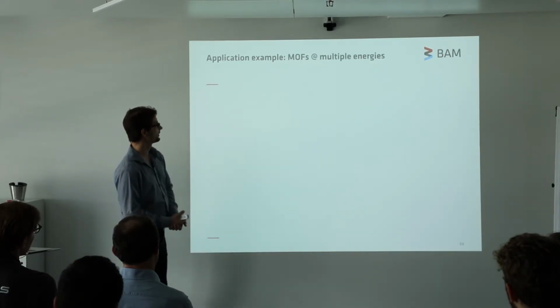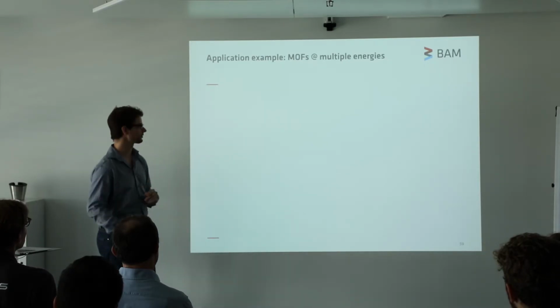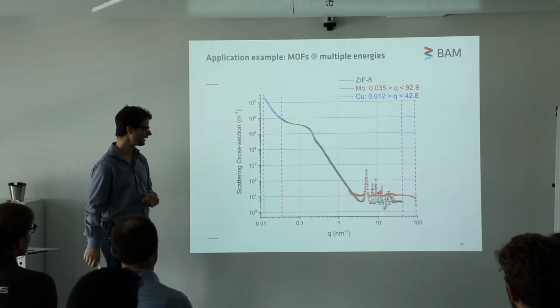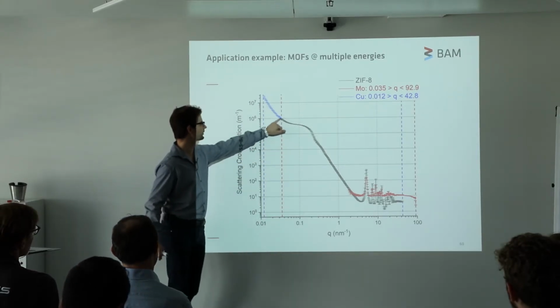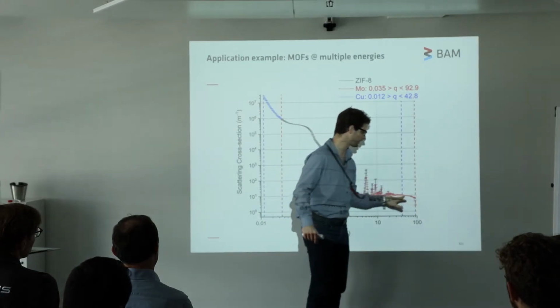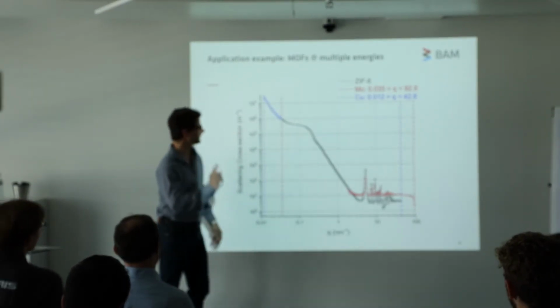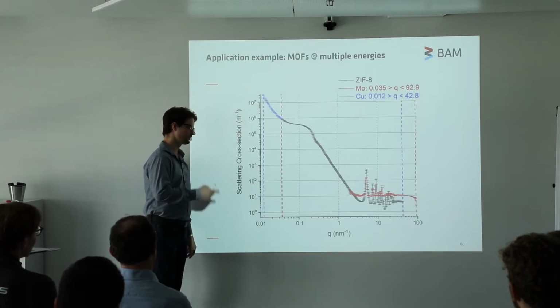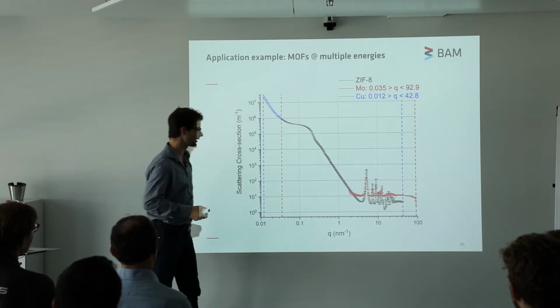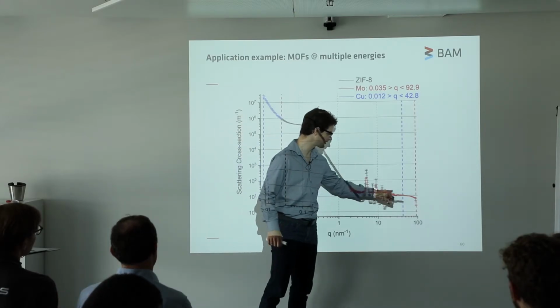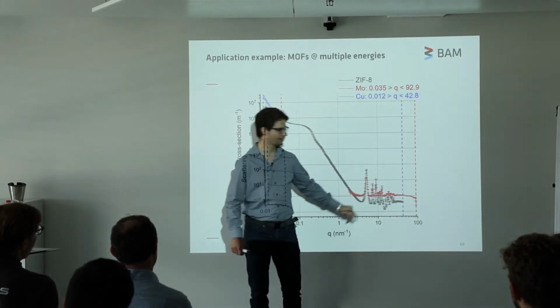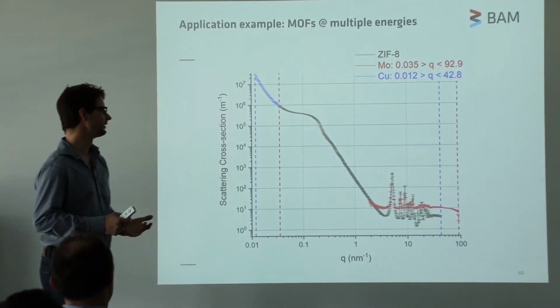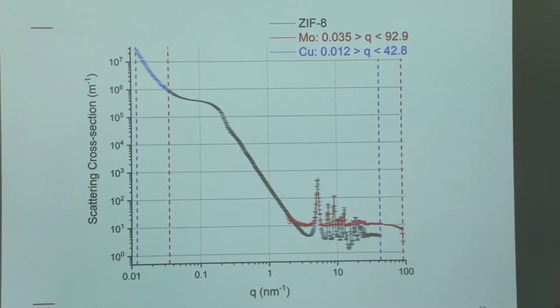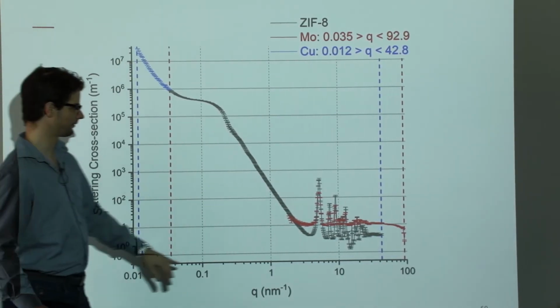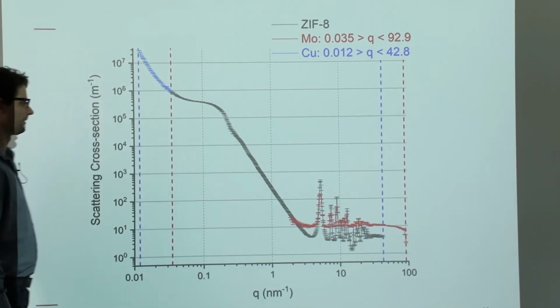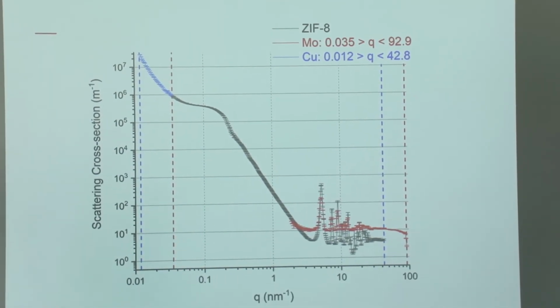We have some interesting things with multiple energies as well. So we have two X-ray sources. We usually try both of them. Usually they give us the same result, except that copper goes a little bit lower in Q, molybdenum goes a little bit higher in Q, but they usually overlap, except in this case. So here we had a ZIF8, which is a metal organic framework, which shows nice crystalline peaks, and these are all the same, but the background is different. And that's because the zinc in the ZIF8 fluoresces a little bit. So it increases the background for the molybdenum source and not for the copper source. So in this case, we have a little bit of fluorescence information about our sample as well.